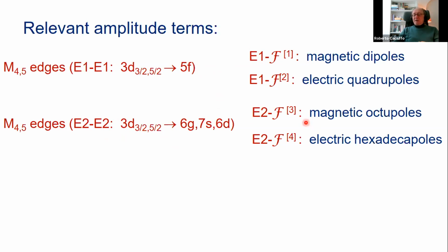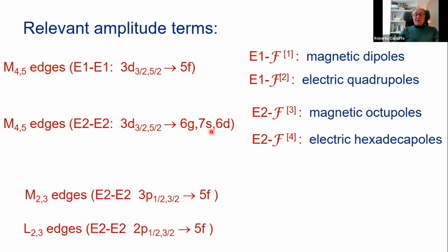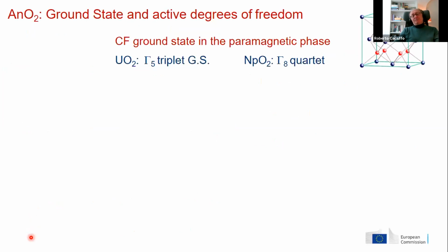other tensorial amplitudes appear that in principle allow one to study electromagnetic multipoles of higher order. However, only indirectly, because in this case, the interrogated shells are 6g, 7s, 6d. If you want to observe directly at the quadrupole edge the 5f state, then you have to go to the M23 and to the L23 edges. Some attempts have been made, but with unsuccessful results.